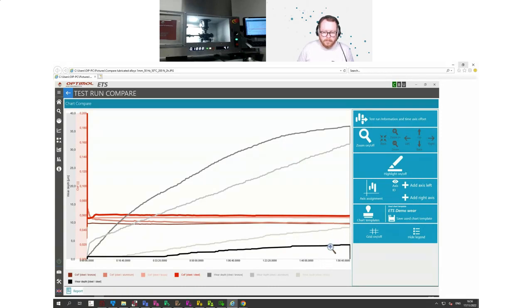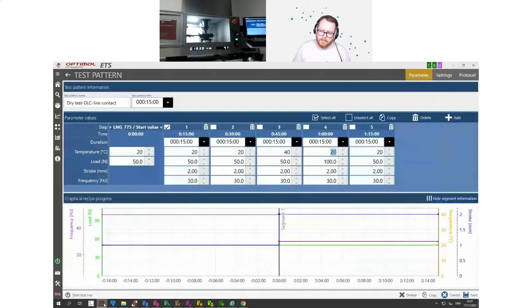For example, the black line is lubricated steel contact with the dark red COF. And for example, the worst performing pairing is the steel against aluminum. In terms of friction, steel against bronze is interesting, but as the surfaces wear quicker than in other cases, the COF becomes relatively low because the surface pressures are reduced, and you have a nice lubricating film between the tribo partners. This is what I wanted to show you before going back to the live view of our test.